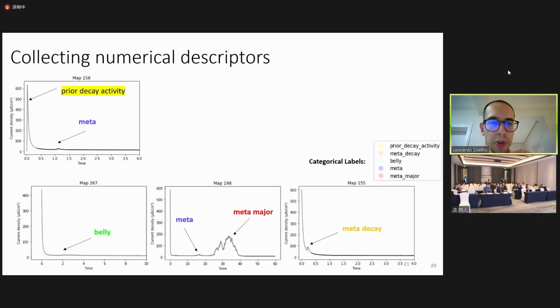We can collect all different types of quantitative numerical descriptors from this type of curves. Each one of those transients that we observe corresponds to phenomena of the pitting process, right? And I can do it, or a corrosion expert could do it, or could distinguish the data very easily. We know that here we have a much more stable pit than in here, for example, and so on. So you could leverage unsupervised learning for trying to cluster the data. But at some point, you should have something to compare against. And we should take advantage of those labels. This is my main message.